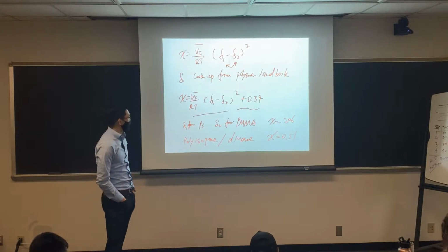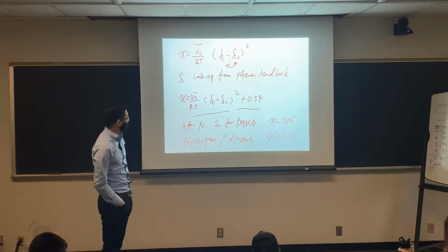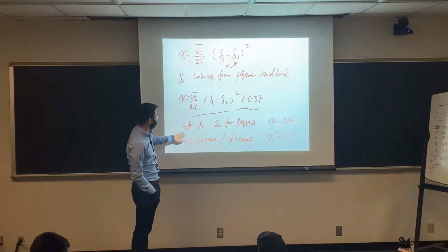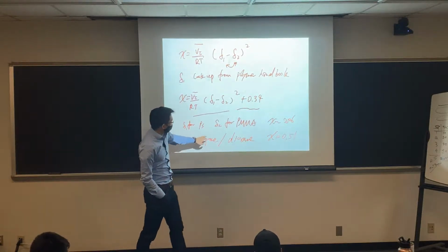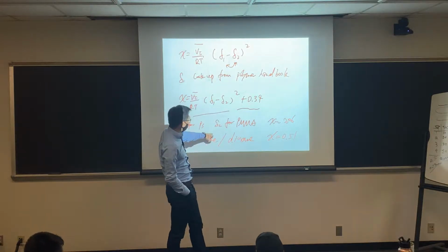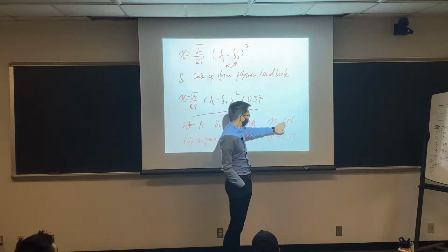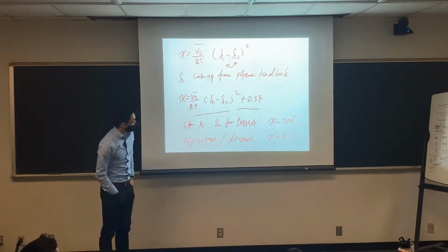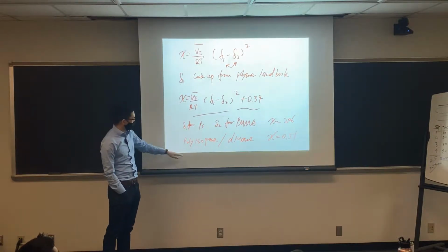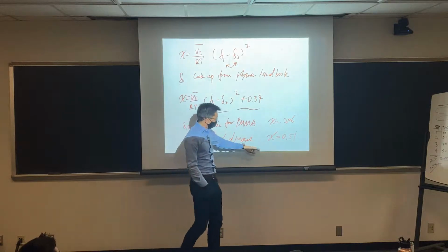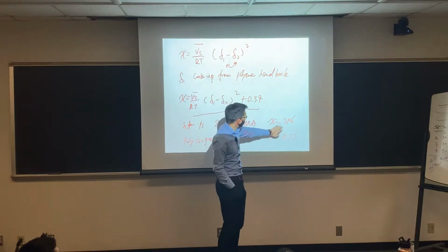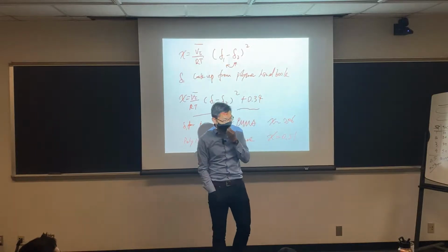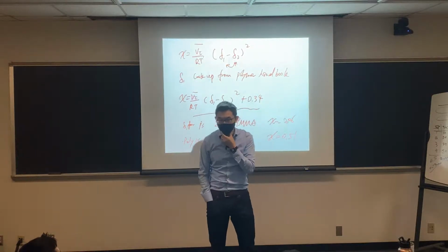And it has worked out better. For example, if we look at using the solubility parameter, we can reach that for delta 1, delta 2. This will be 0.06. So polystyrene and PMMA are relatively compatible, but isoprene and dioxane is not. And these values are based on the top equation. If you want to calculate more carefully, they will be even higher.